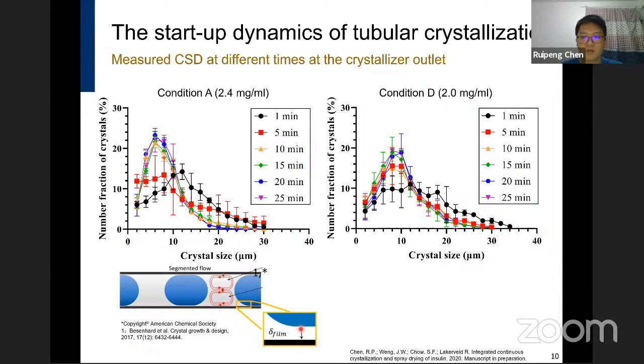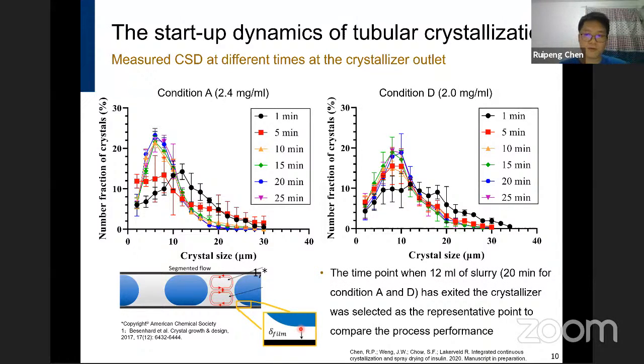We also monitored the insulin recovery for other operated conditions, and it was found that for most of them, they reach a plateau when around 12 ml of the product slurry has exited the crystallizer. This is 20 minutes for condition A and D. Therefore, this time point was used as a representative point to compare the process performance.